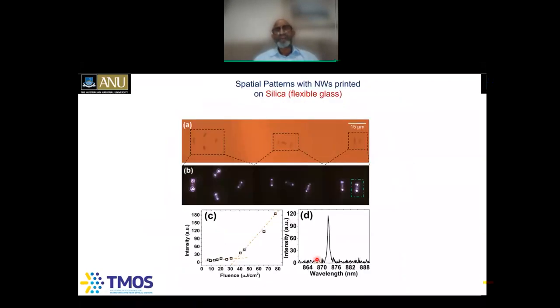You can see that these are the nanowires. They are transferred onto a glass substrate, a flexible glass, because we want to use it for flexible optoelectronics applications. You can see there are about 4 nanowires here, 3 here, 2 here, and we pump these nanowires with the laser and look at the light emission. You can see that the light is coming from both ends of the nanowire, because each nanowire laser acts like a Fabry-Perot cavity, indicating that all of them are lasing, and that this is a gentle process. We have not created any damage during this transfer process. You can see again threshold-like behavior and narrow line width, showing that all these nanowires are really lasing.